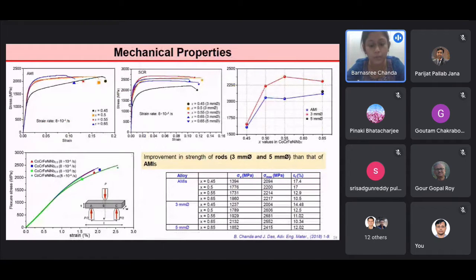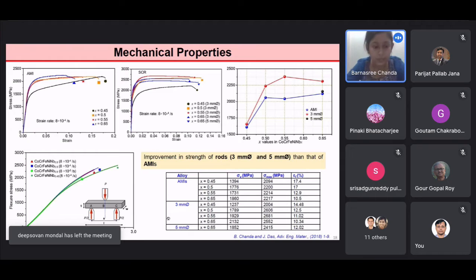The mechanical properties have been evaluated by room temperature compression test, and at 0.45 with FCC proeutectic phase, the yield strength is lower as compared to other compositions. This is because of the higher volume fraction of the soft FCC phase, and as we add niobium, the hard Laves dendrite increases the yield strength, but at the cost of limited strain. A similar observation can be seen in case of the suction casted rod, and when we compare the yield strength of the suction casted rod and arc melted ingot, an improvement in the yield strength can be seen in the suction casted rod with the highest cooling rate. Further, the 3-point bend test has been performed, which showed noticeable ductility at different strain rates.